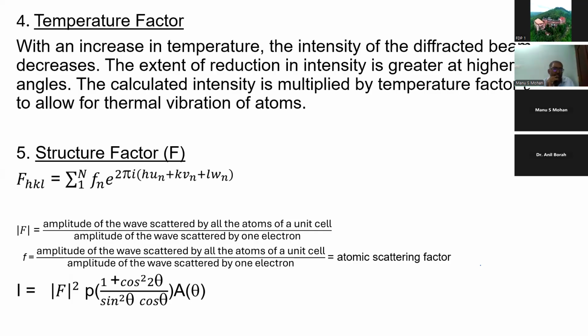So the structure factor is basically the product of the phase difference factor between two electron waves, two X-rays, which is taken into consideration by e power 2 pi I into hx plus ky plus Lz. That phase difference part is taken care of by that factor, times the atomic scattering factor. The atomic scattering factor is nothing but the ratio of the amplitude of the wave scattered by all the atoms in the unit cell to the amplitude of the wave scattered by one electron.